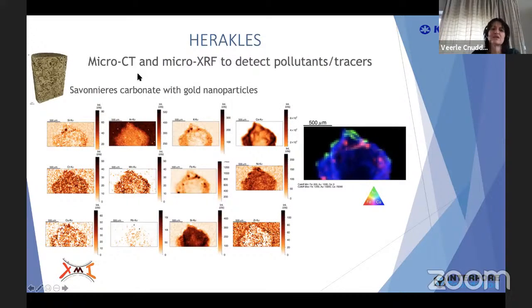I tested this on a limestone where I added gold nanoparticles, on average 13 nanometer diameter. I added them onto my Savonnieres, and then I wanted to see if this signal was picked up with the XRF.